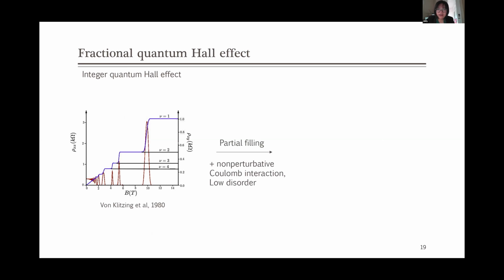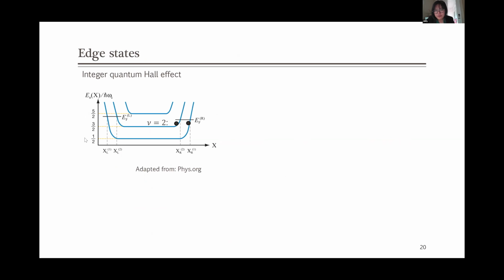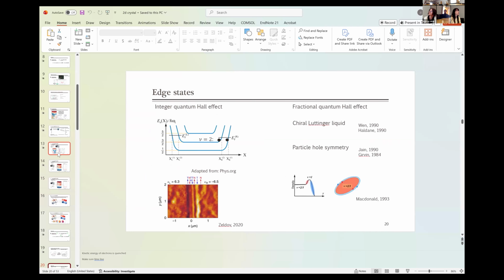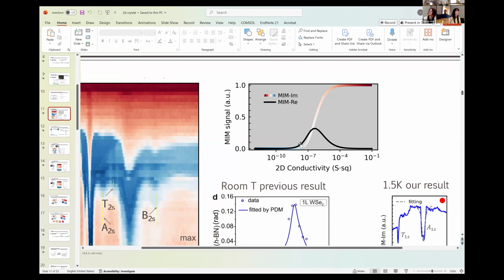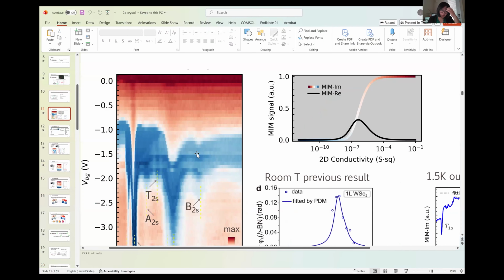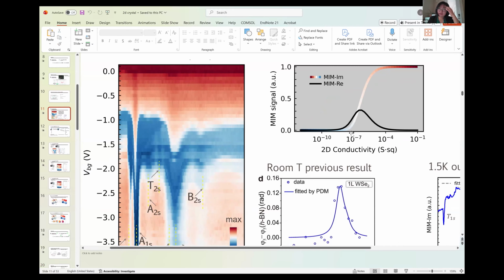So what we found for the TMD is that its conductivity is a pretty rapidly changing function of its doping. In this graph, in the specific case of using TMD, we can reach a pretty insulating regime of the 2D conductivity, 10 to the minus 7 or even lower, for a certain range of doping that we needed.